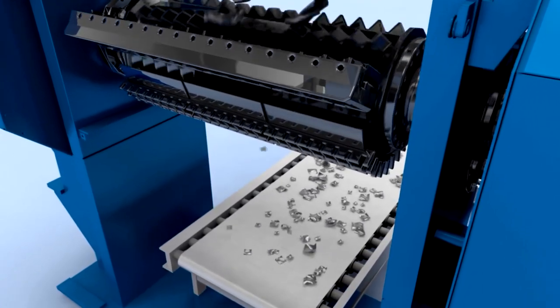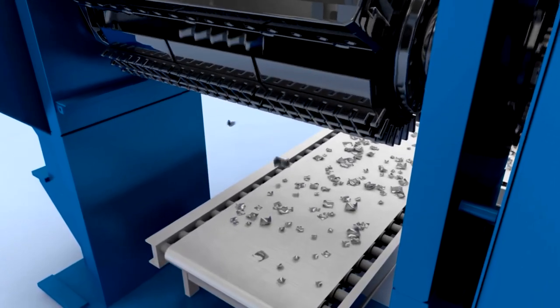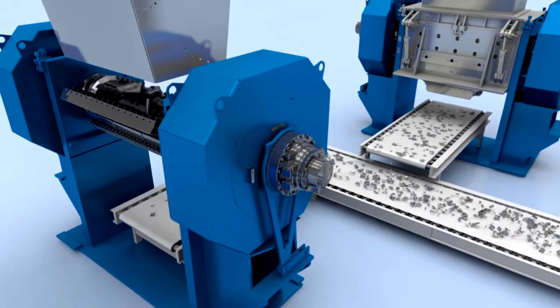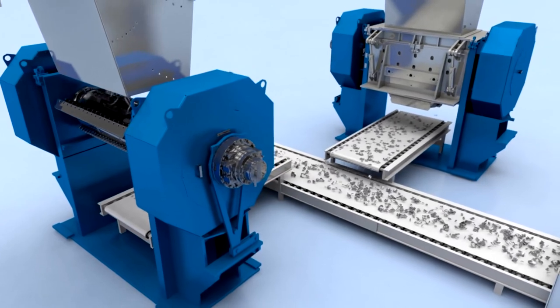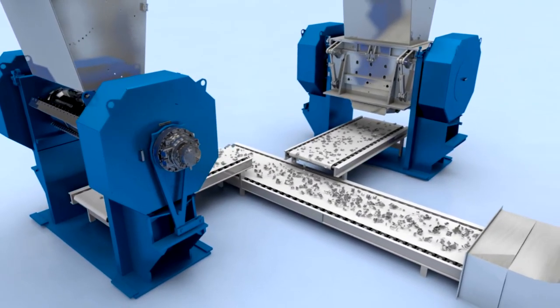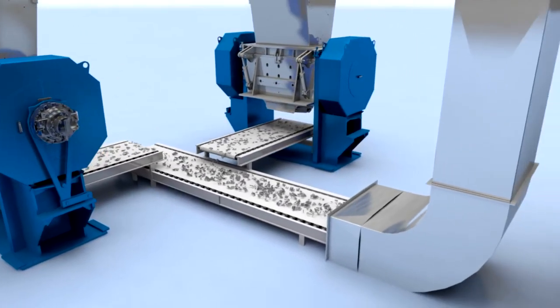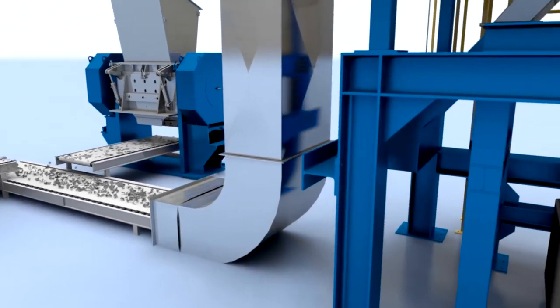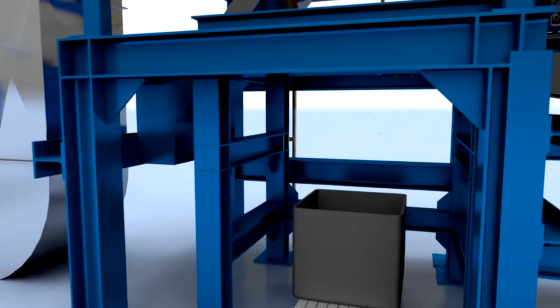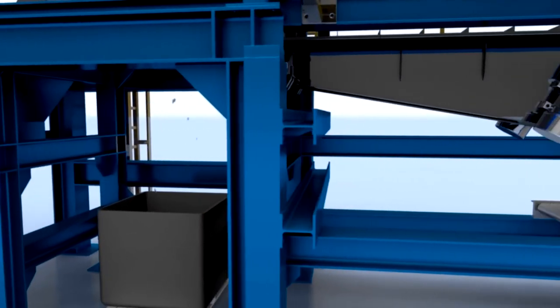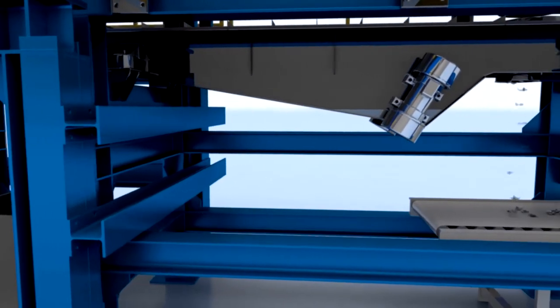When blending undesired tramp elements into such established alloy grades, some of these properties can substantially worsen, for example, through the change of the precipitation kinetics, segregation, the formation of undesired and large intermetallic phases, or changes in the precipitation-free zones that surround the decorated grain boundaries.